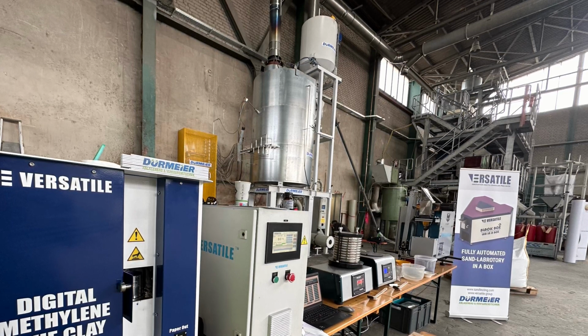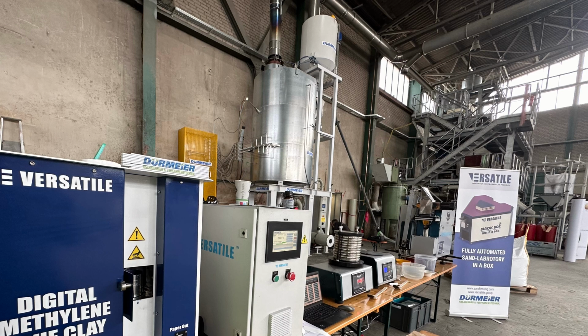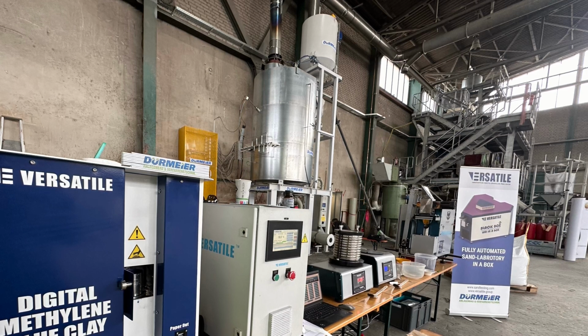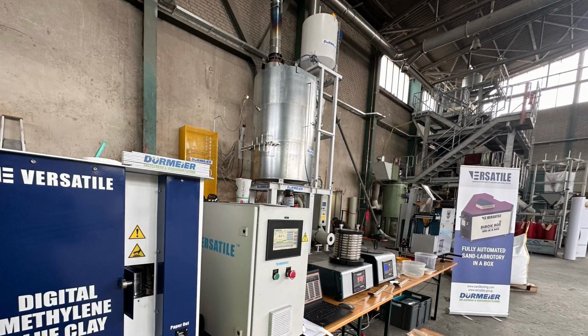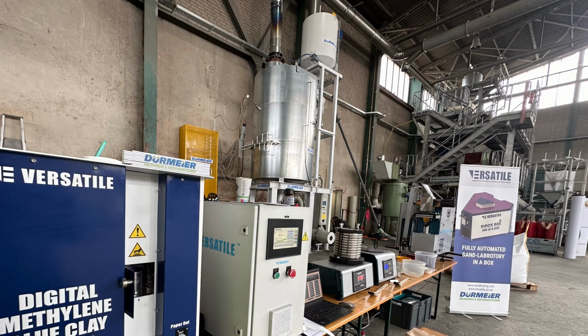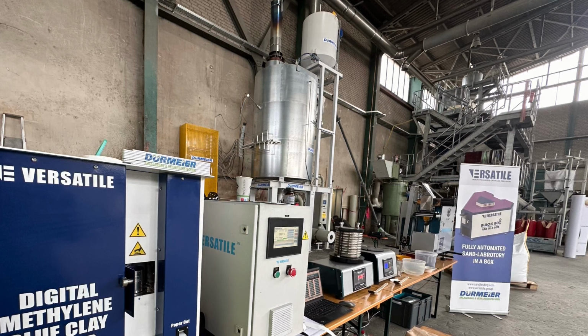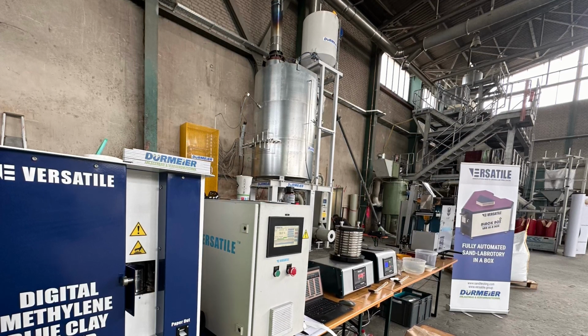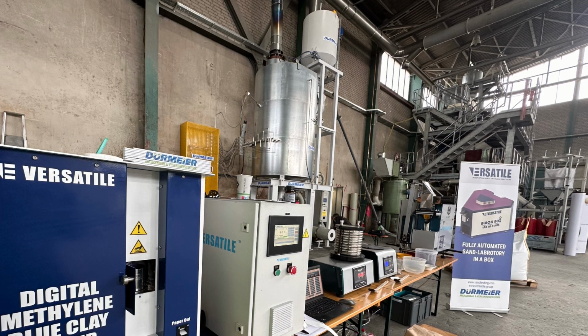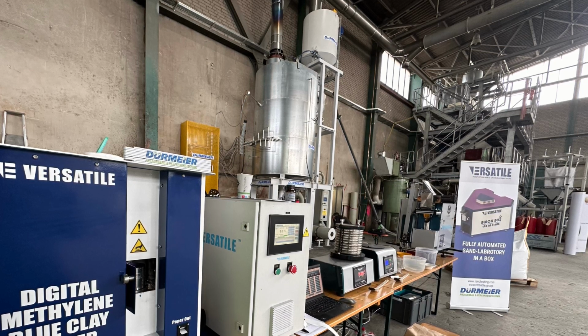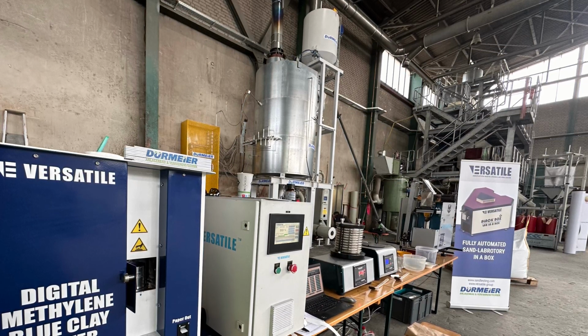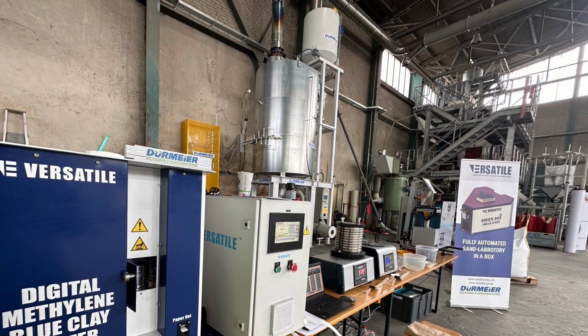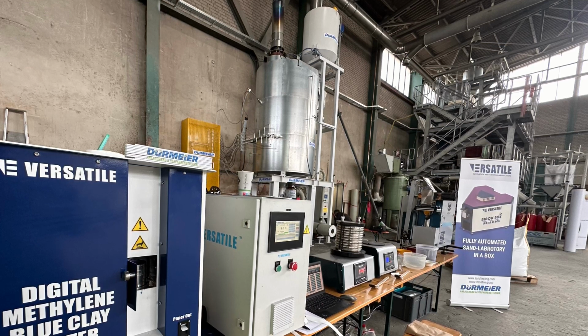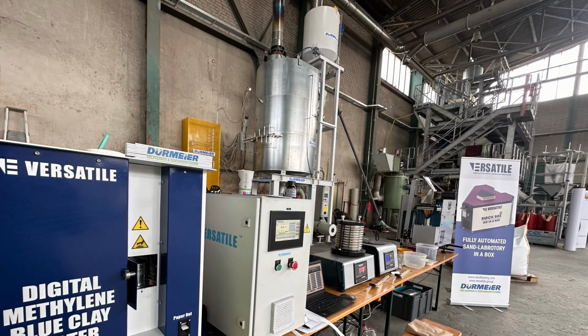Got it. And what about the gases? You mentioned gases being generated. How do they make sure those can get out? That's permeability. Permeability is just a measure of how easily gas can flow through the sand mold. Right, like how breathable the sand is. Exactly. It's critical for preventing gas defects. If the gases from the metal hitting the moist sand or from binders burning off can't escape through the sand pores, they get trapped in the metal. Oh, wow. So you test the permeability.